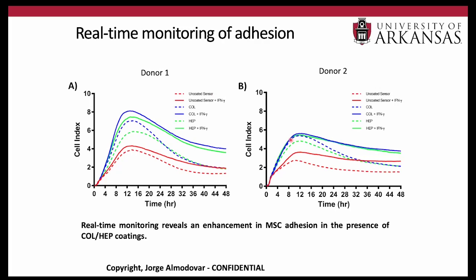All right, so then we went ahead and did another study with that impedance-based assay. And again, here, similar to the Schwann cells, what we saw is that, you know what, there is a difference in cell adhesion. The curves here in blue and green are conditions where we have our surfaces, our collagen heparin coatings, and the cells adhere much more strongly than on the uncoated surface. And we saw this with cells from two different donors. So our surfaces really do something to that cell adhesion as well.